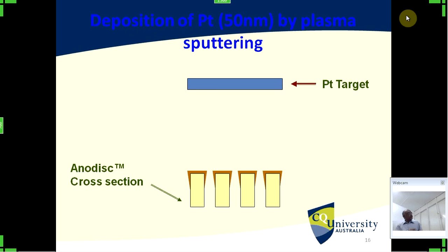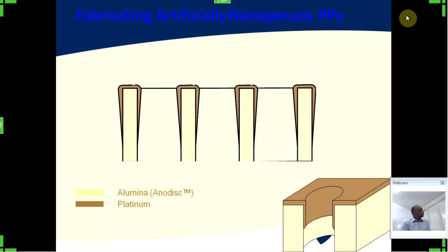you develop a platinum layer on top of this one. There will be a thick layer on the flat surface, and a thinner layer going into the hole like this, because the platinum comes from this platinum target. This happens under high vacuum and at a higher voltage. When the platinum particles are released from the target, they fly randomly and land on the flat surface. Those that escape the flat surface go through the hole, and the thickness diminishes as it goes down. This is the first step, alumina and the platinum layer.